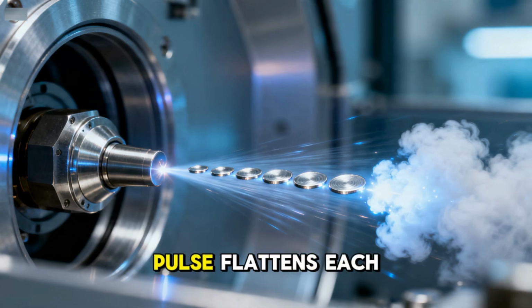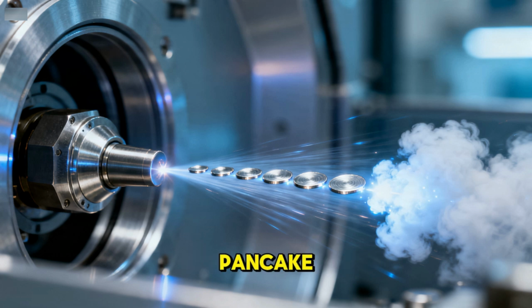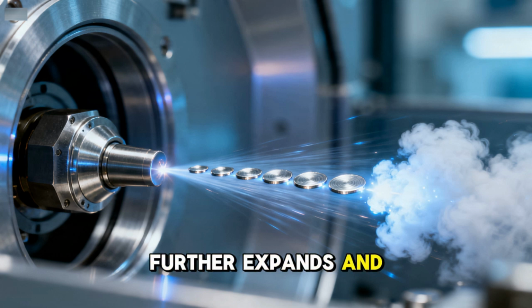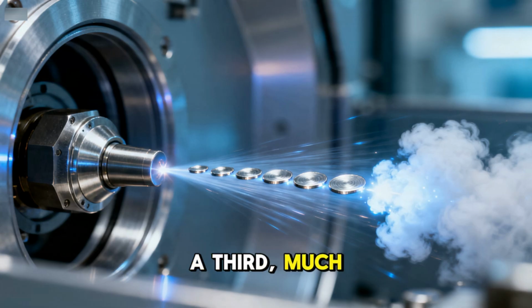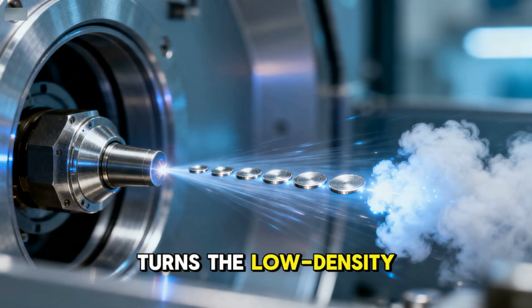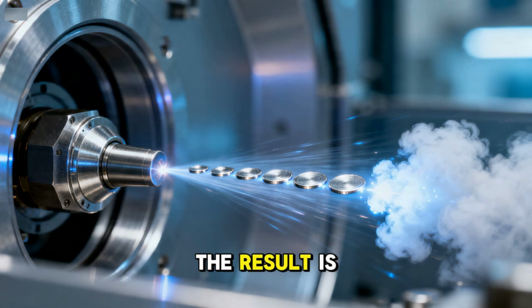A first laser pulse flattens each droplet into a pancake. A second pulse further expands and rarefies it. A third, much more powerful pulse turns the low-density cloud into plasma. The result is a flash of 13.5 nanometer light.